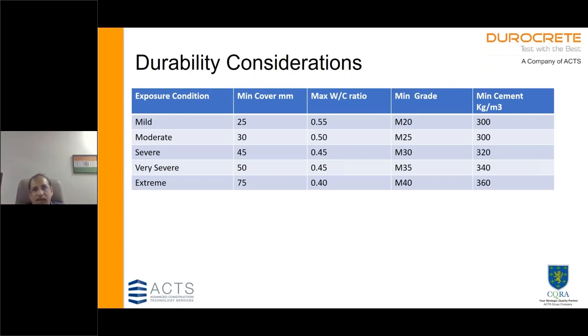And for each condition of exposure there is a maximum water cement ratio, minimum grade, and minimum cement content. Basically all these criteria are related to permeability of concrete, the maximum water cement ratio and minimum cement content. Because lower the water cement ratio, lower is the permeability. And we need certain minimum cement paste volume to create that imperviousness. So minimum cement content is also defined.